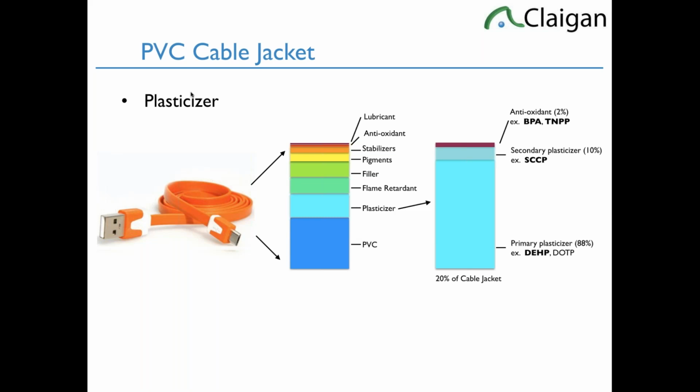And there's usually a bit of antioxidant, which is commonly bisphenol A. So bisphenol A is a very common antioxidant for orthophthalates. So the plasticizer itself will have an antioxidant, and that antioxidant will be in higher concentrations than the antioxidant for the PVC itself. It'll be up to 2% of the plasticizer, maybe a little bit less, maybe about 1% or less. However, in the final product, you'll end up with a couple thousand ppm of BPA. So when we see a BPA non-compliance over 1,000 ppm in PVC, it's normally coming in through the plasticizer, not through the PVC itself. It's coming in as an antioxidant.